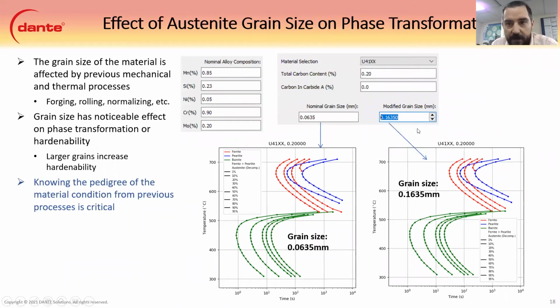And then the grain size works the same way. You can see the grains here, we had a larger grain size, and you can see the difference in the phase transformation timing here. It is very slight, but you can still see the difference, since it is only an extra 0.1 millimeter grain size. But there you can see this is at 1 second, and then here this is later than 1 second for the 1% bainite nose. And larger grains will increase hardenability.